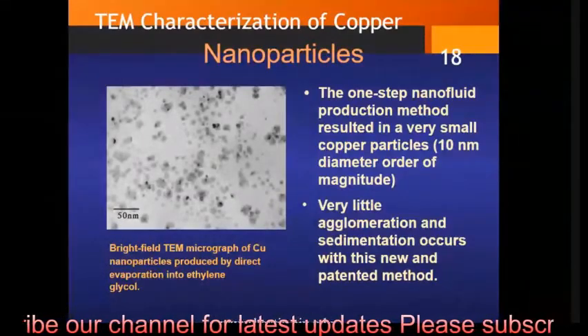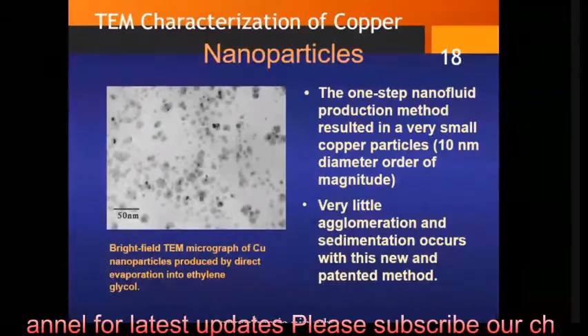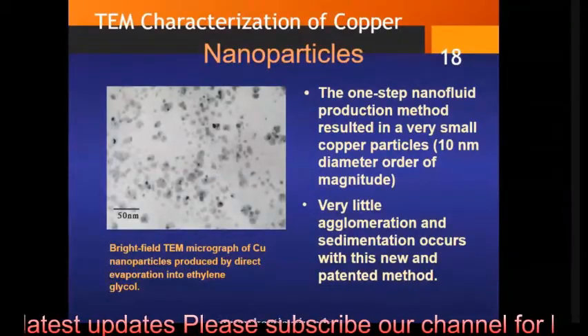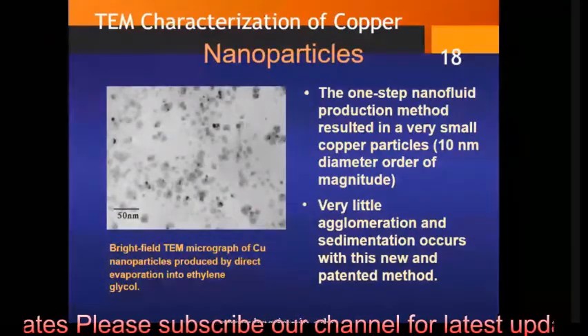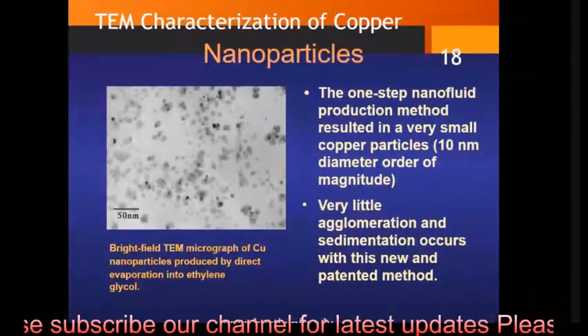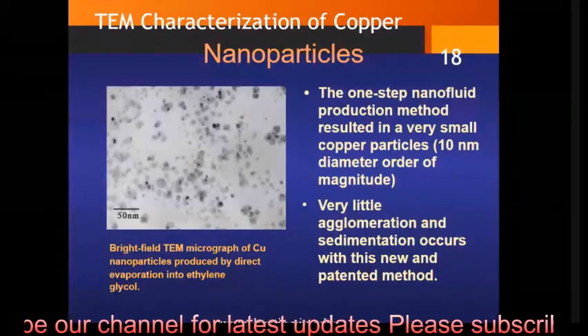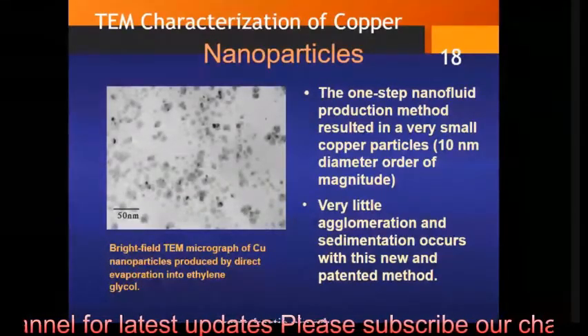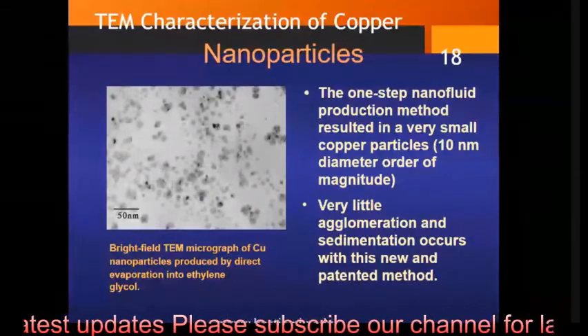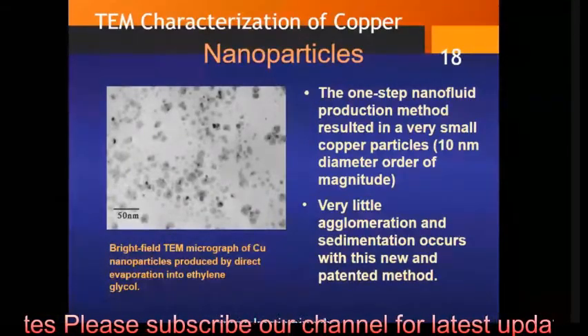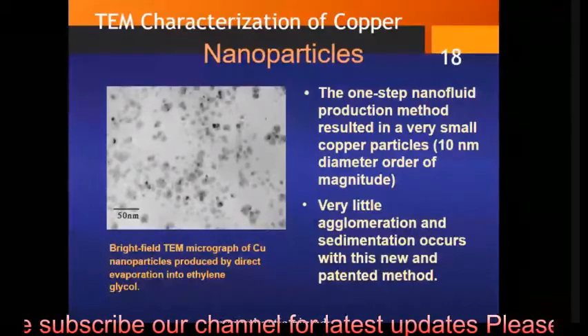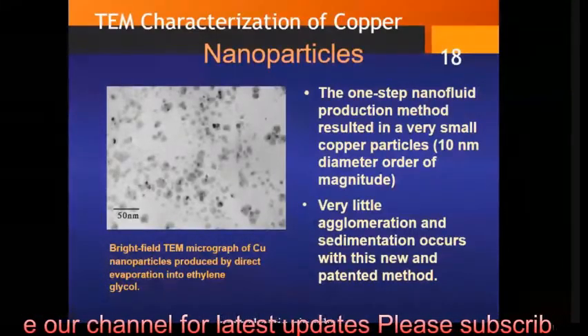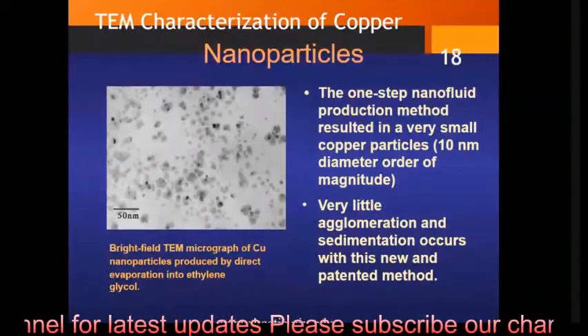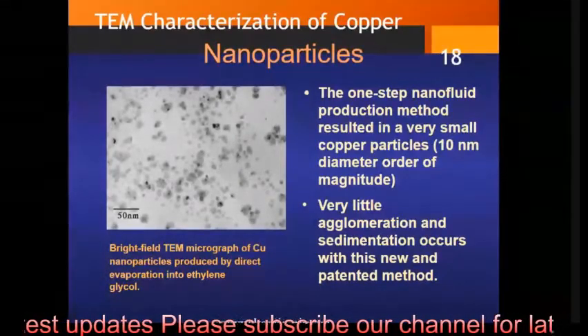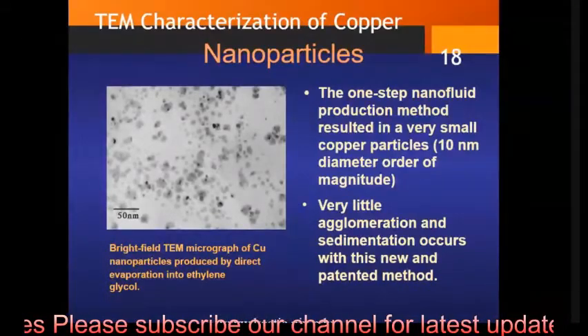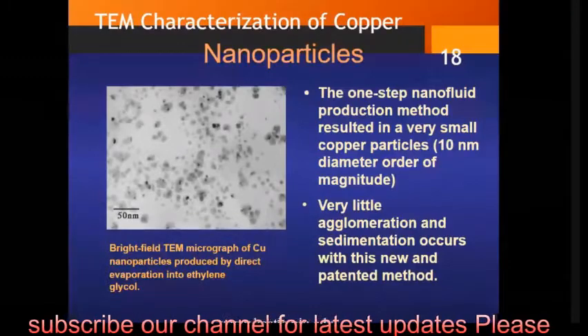embedded in the fluid structure, of course we started scanning the systems for imaging like TEM. The figure shows the TEM characterization of copper. The bright field TEM micrograph of copper nanoparticles produced by direct vaporization into ethylene glycol is shown here. It exhibits that the one-step nanofluid production method resulted in very small copper particles, 10 nanometer diameter in the order of magnitude, and very minimum agglomeration and sedimentation occurs with new and patented methods for specific applications.